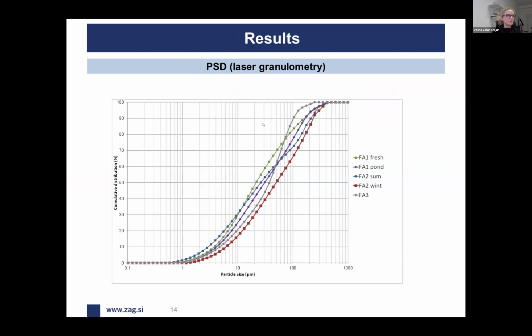The first thing was characterizing the physical properties, so particle size distribution. It's quite obvious that if we compare the fresh and the pond one, so the green and the purple one, the ash collected from the pond is larger grained, and also the winter in comparison to the summer regime, FA2, is somewhat larger particle sized because more wood chips are used. The narrowest particle size distribution is shown by FA3.